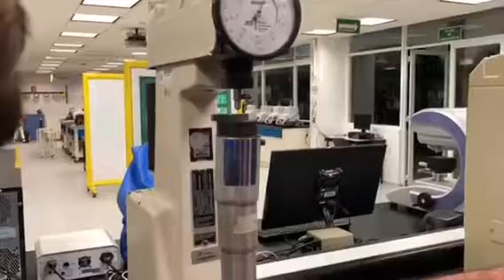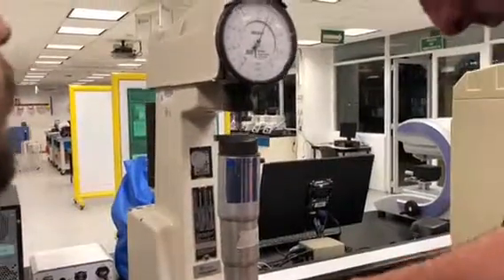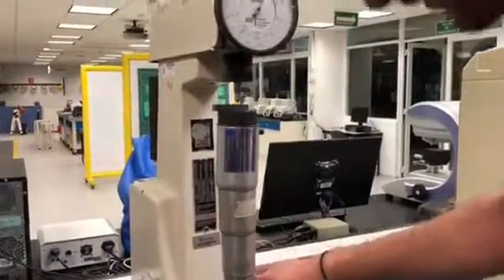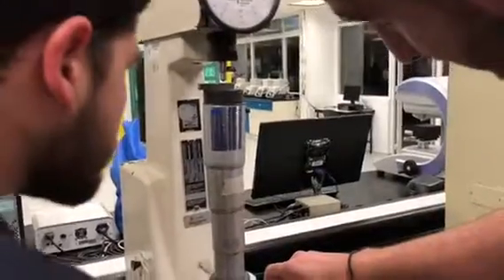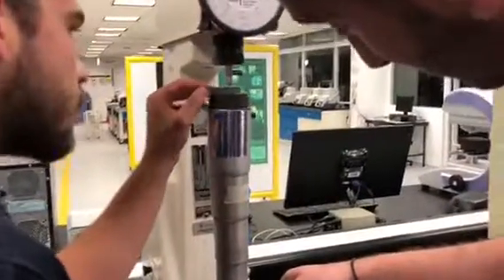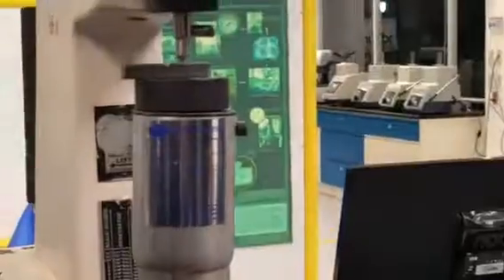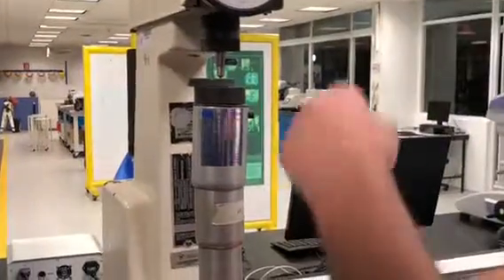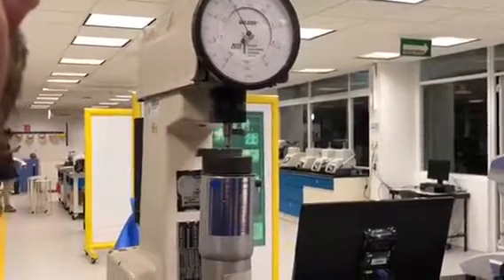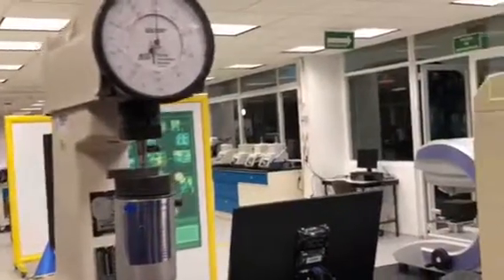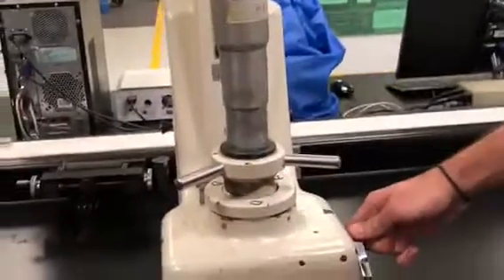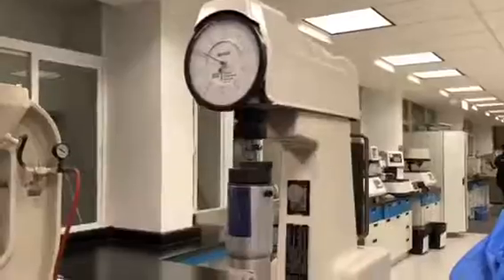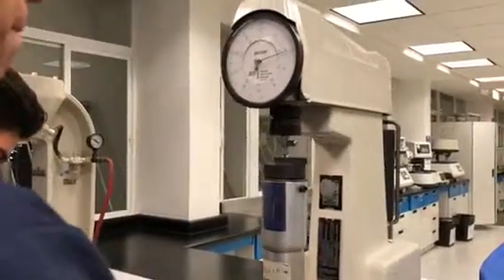The Rockwell test determines the hardness by measuring the depth of the penetration of an indenter under a larger load compared to the penetration made by the preload. For this test, the sample is kept in the center and pressure is applied by actioning manually until the indicator needle turns 2 times and is kept in 0. The lever is pushed forward and then taken back once the needle stopped moving. The needle indicates the resulting hardness in the HRC scale.